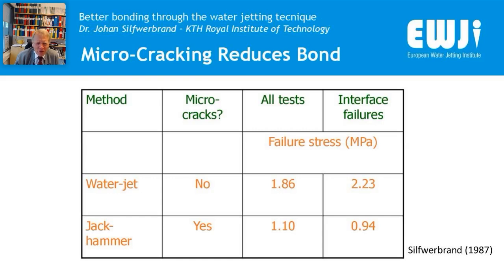This has a rather important influence on the bond. So if you compare, and this I did in my PhD thesis, it is a long time ago, but the results are still valid. Here was a comparison between water jet and jackhammers. You can see that we have microcracks in the jackhammer, and we obtain a failure stress, a bond strength, of about 1 megapascal for that case. And if we use the water jet technology, we received twice as high